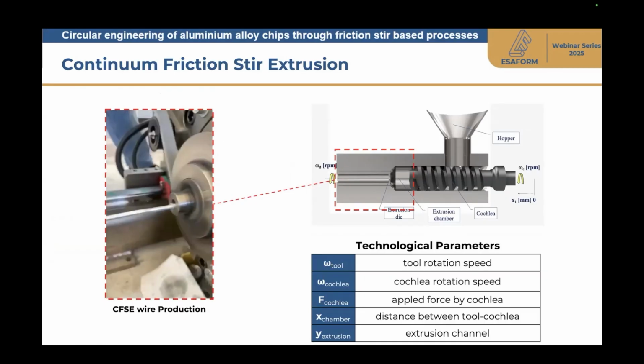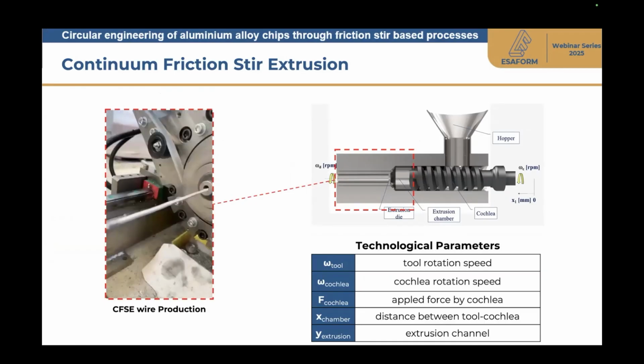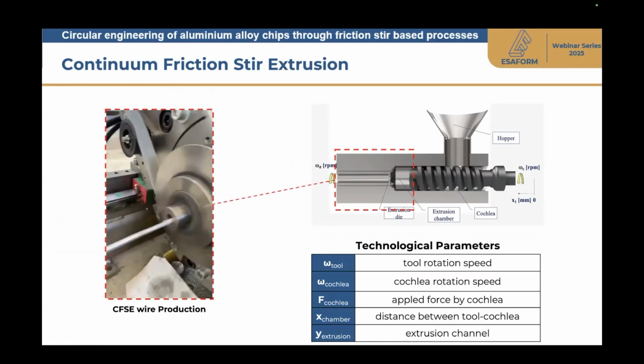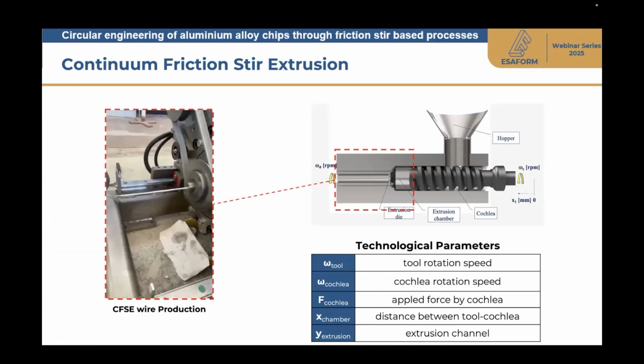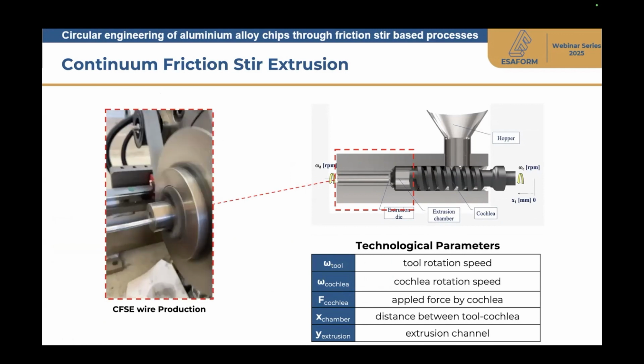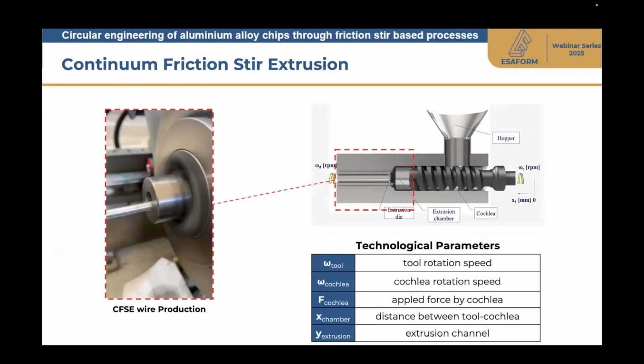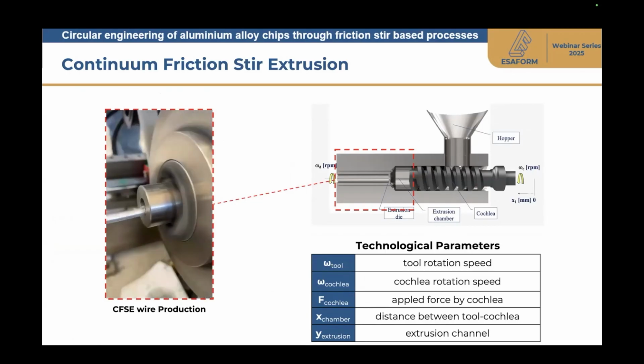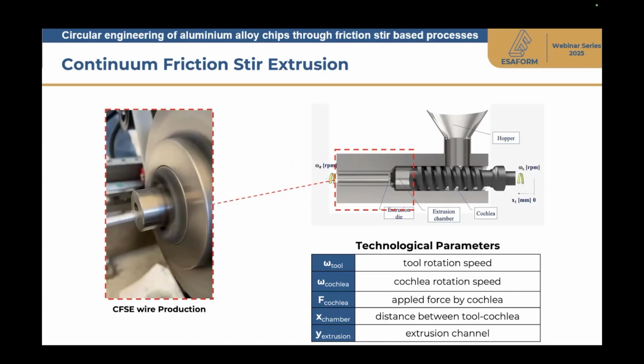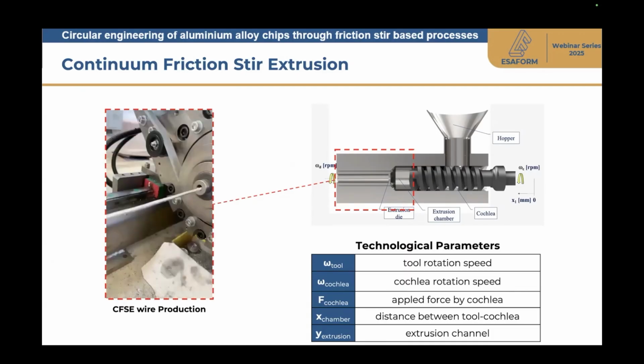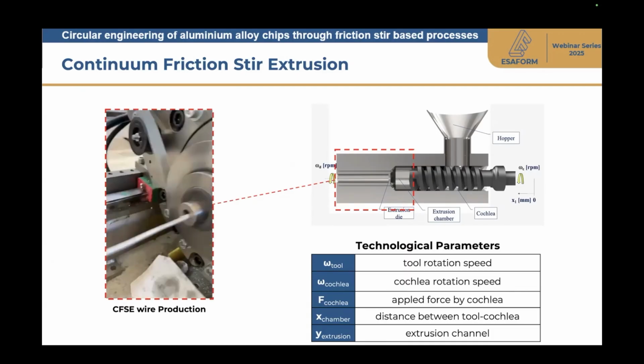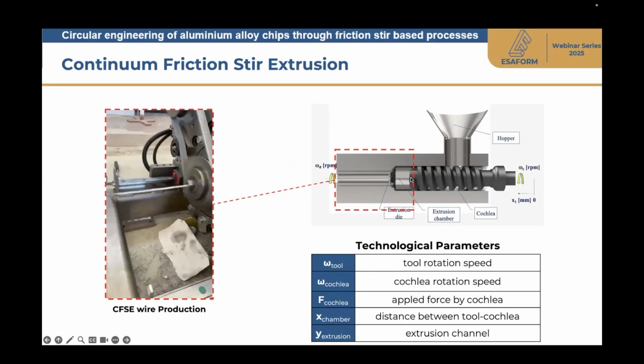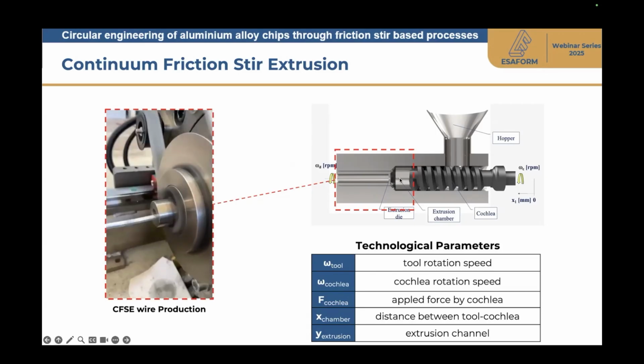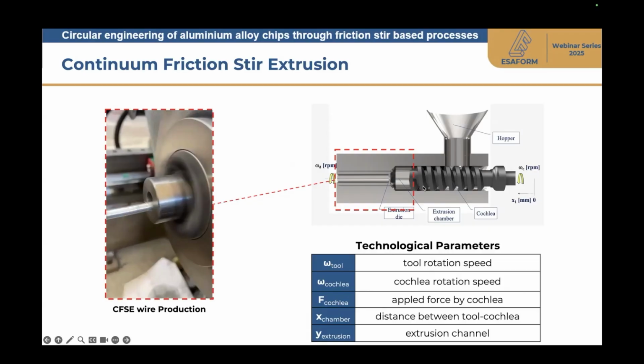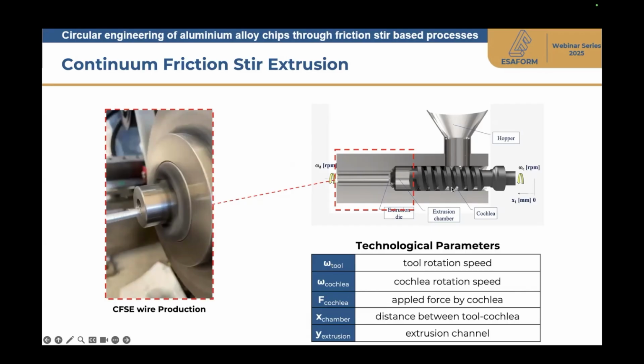And you have a very complex setup of the machine, but also a very complex process engineering, since you have to properly tune the tool rotation speed, so the extrusion matrix rotation speed, the cochlea rotation speed, the applied force by the cochlea, but also some distances, for instance, the actual height of the extrusion chamber, since such height determines the amount of material which can be contained and pressed just in front of the extrusion tool, and so on.